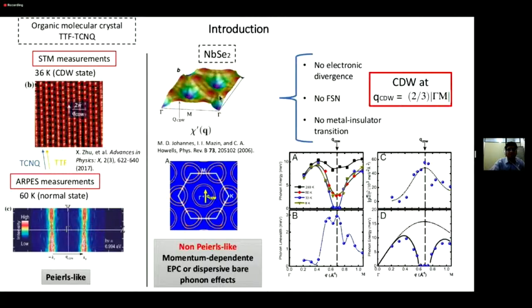Actually, for the case of the transition metal, this kind of niobium selenide, the explanation is given by a strong electron-phonon coupling for exactly the wave vector that gives the CDW. Here they can obtain this from measurements of phonon linewidth. But there should be many other roads to explain charge density wave.